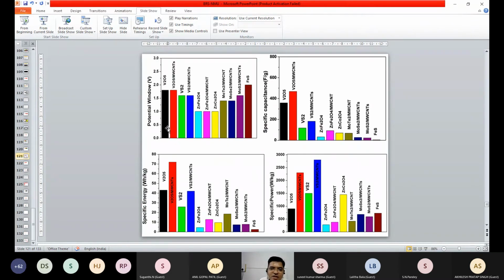And here you can see that the potential window we have reached for vanadium oxide is 1.8, vanadium sulfide 1.6, and most interestingly, iron sulfide, which is deposited on stainless steel, right? In the device, you can see that the voltage window we reached is up to 2 volt, a very high value. That is, it reached up to 2 volt for the solid state device.